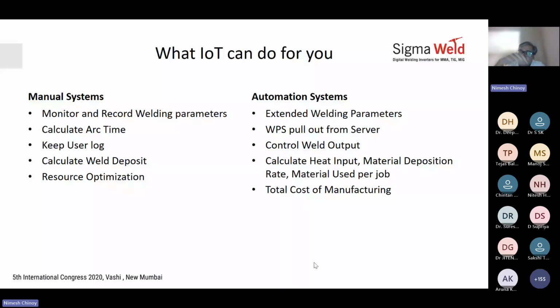So if you said, I'm going to join these 2 materials today, then it will go to the server, pick up the job number, the joint number, the welding current and voltage it is supposed to weld at, the welding speed it is supposed to weld at, and it will start welding at those parameters only. You can also control the weld output. You can say in an automation that it will not go above and beyond this particular range, so it will not allow it to go. You can calculate heat input, because once you have speed, you can have heat input in place. You can calculate material deposition rate, how many kgs per hour you did, or how much material was used per job. And you can evaluate the total cost of manufacturing.